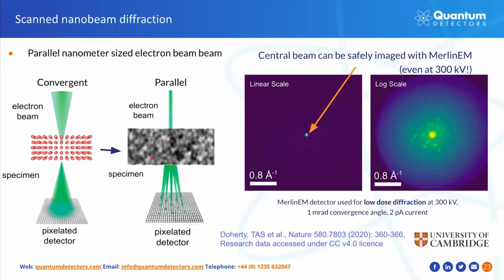The couple of images on the right demonstrate what a single diffraction pattern in nanobeam diffraction can look like. Images were collected with 300 kV illumination with a small 2 picoamp current. We can see that the sensitivity of the detector needs to be very high. If we plot the data in the linear scale, as shown on the left side here, all we see is a sharp central diffraction beam. To visualize the information actually present in the data, we need to switch to logarithmic scale to see all the spots generated through the diffraction process. And this was done on the right side here. Importantly, no beam blankers need to be used in diffraction due to the radiation hardness of the MerlinEM detector.